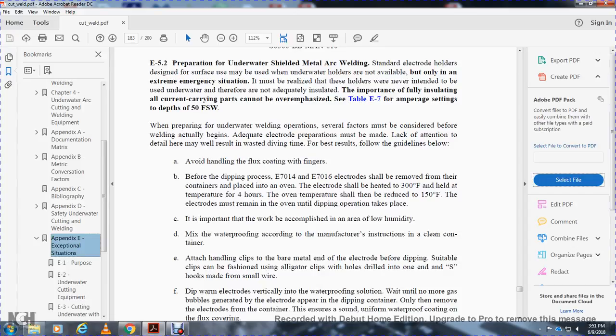When preparing for underwater welding operations, several factors must be considered before welding actually begins. Inadequate electrode preparation, or a lack of attention to detail here, will result in wasted diving time. For the best results, follow the guidelines below. Avoid handling the flux coating with the fingers before the dipping process. E7014 and E7016 electrodes should be removed from their containers and placed into an oven. The electrodes should be heated to 300 degrees Fahrenheit and held at that temperature for about 4 hours. The oven temperature should then be reduced to 150 degrees. The electrodes must remain in the oven until the dipping operation takes place.